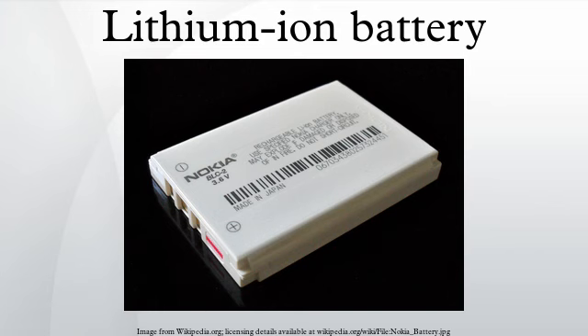Electrolytes. The cell voltages given in the electrochemistry section are larger than the potential at which aqueous solutions will electrolyze. Liquid electrolytes in lithium-ion batteries consist of lithium salts, such as LiPF6, LiBF4 or LiClO4 in an organic solvent, such as ethylene carbonate, dimethyl carbonate, and diethyl carbonate. A liquid electrolyte acts as a carrier between the positive and negative electrodes when current flows through an external circuit. Typical conductivities of liquid electrolyte at room temperature are in the range of 10 mS/cm, increasing by approximately 30–40% at 40 degrees Celsius and decreasing slightly at 0 degrees Celsius.